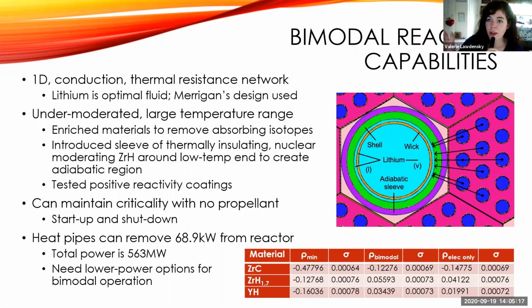So, after investigating how a single heat pipe would function, because it's replacing a huge moderator element, we found that the zirconium carbide, the best one in the previous analysis, was getting a negative reactivity at its max. Showing there is the max, the bimodal and electric only. And that obviously won't work. No nuclear reaction, no propulsion, no electricity. But the hydrides that we excluded for having that positive minimum reactivity worked pretty well here. They had negative minimum and they had positive in both configurations.